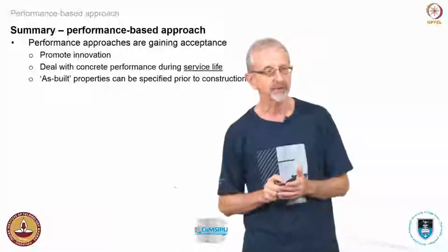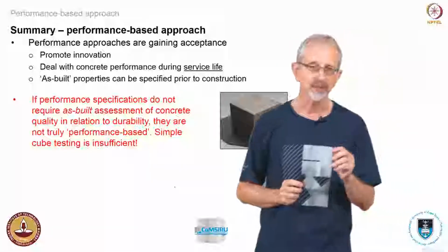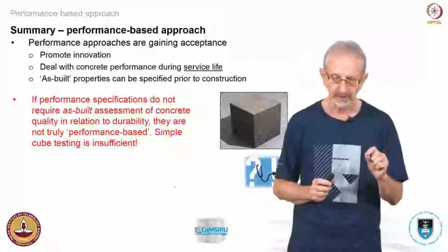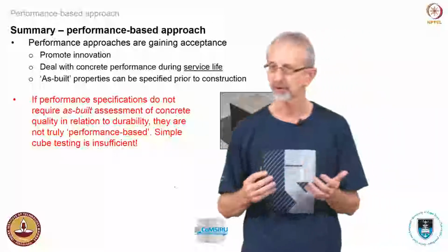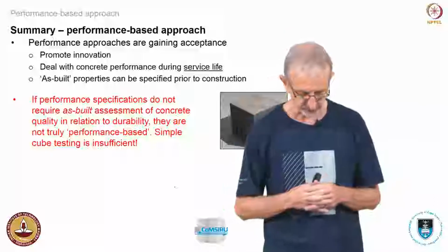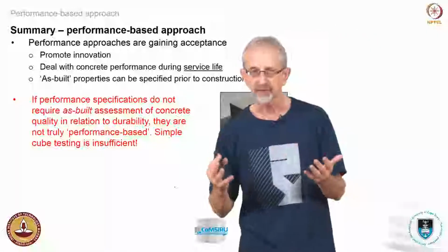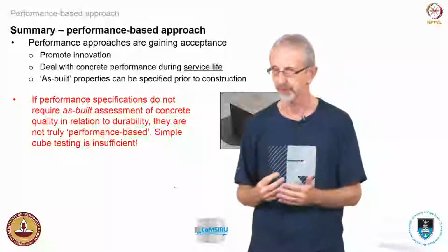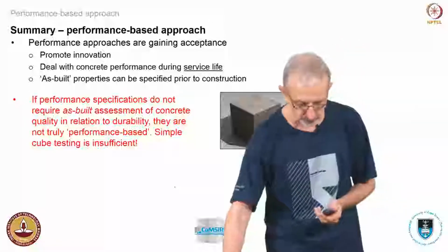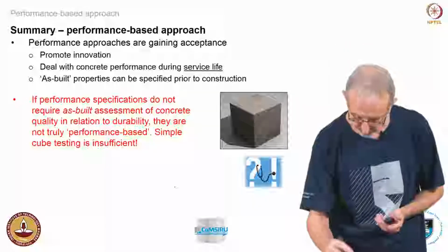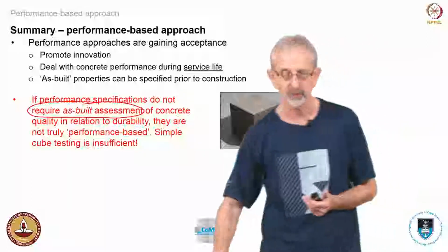The as-built properties are specified prior to construction, but if we do not measure these performance requirements within the real structure, for example in relation to durability, then in my view these are not truly performance-based specifications. You can't simply do cube testing. And some approaches that you find in the literature, which are called performance approaches, in fact are not, in my view, because they do not go through to this final very important step of requiring as-built assessment. And that is always a trick.